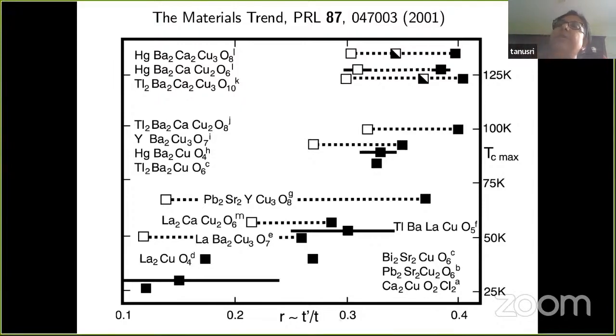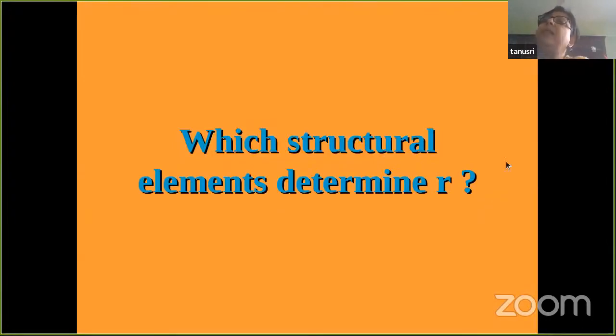while this R parameter is basically calculated from the Fermi surface plot. And you can see a really nice correlation between this R parameter and the Tc at optimal doping. Now, the question we asked: which structural elements determine this R?